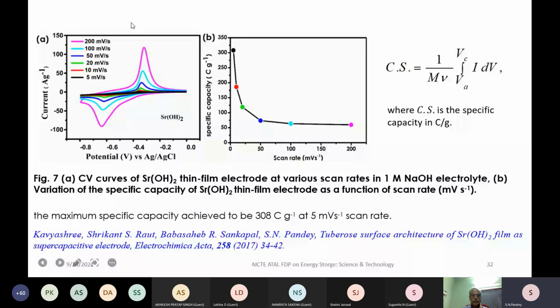And then we have seen that as we increase the scan rate, the specific capacity decreases. So it has the maximum value at 5 millivolt per second. The maximum specific capacity achieved is 308 coulomb per gram at 5 millivolt per second scan rate.